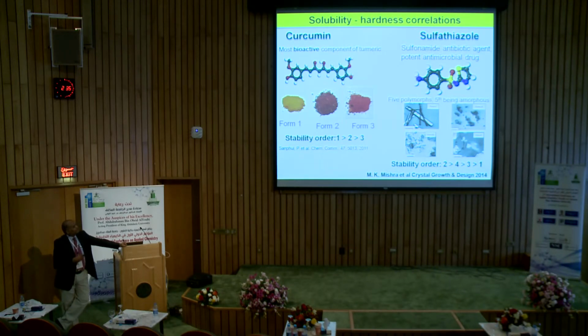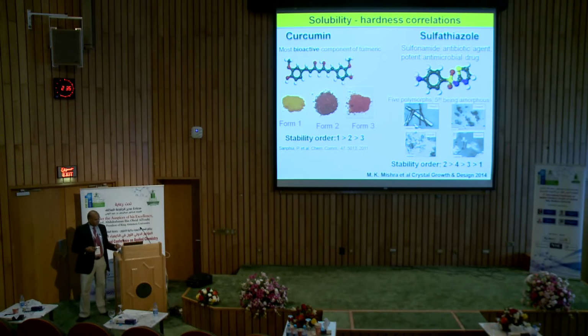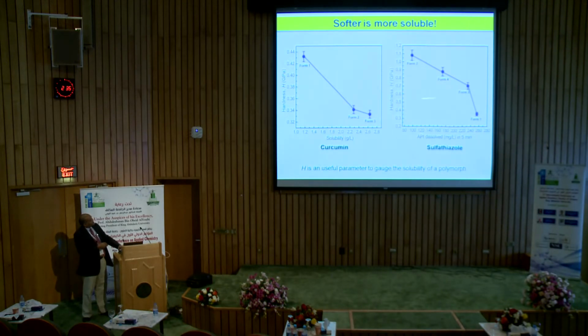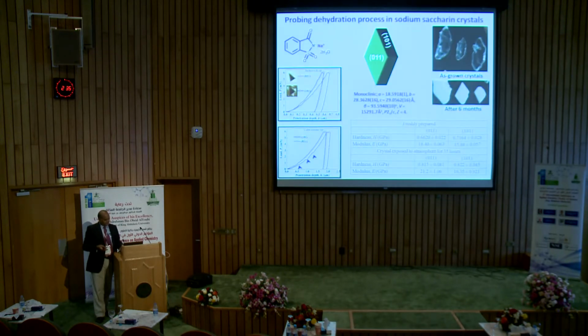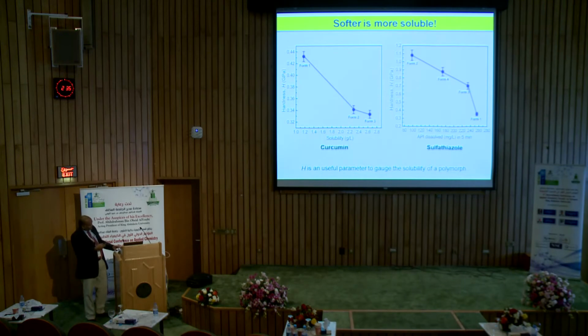The reason is solubility is very important. If you take a drug, it has to be dissolved in your system so that it's medicinally useful. Otherwise, it's not. So we checked curcumin and sulfathiazole, and we actually see that the solubility correlates very well with hardness. So this is a useful parameter because hardness is something that you can measure straight away. And as we say, softer is more soluble, so the material is easy to dissolve. The softer it is, the easier to dissolve.